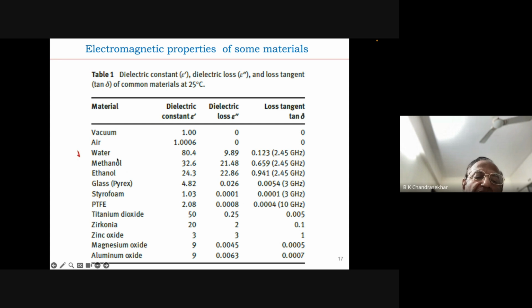So obviously, if you have a material like methanol or ethanol, you should not put it in a microwave oven, because the dielectric loss is very, very high. And they are also combustible materials. So if you put them inside a microwave oven and switch it on, the chances of an explosion are very high.